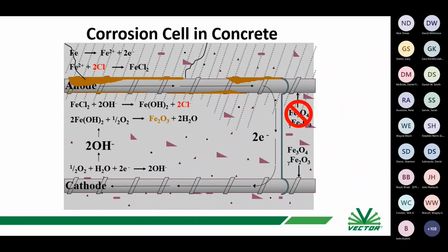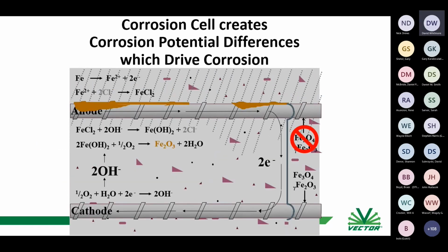So people are generally only concerned about the physical impact of this reaction that's happening inside the concrete. And that's okay, because that's ultimately what's causing the damage. But it's important to understand what's causing that physical change in materials. Okay, so I said very simply that the chlorides getting in there cause this to happen. That's true. Or if it becomes carbonated, that will cause this to happen. But there's really one other part of the equation that you can see very clearly when you go and do certain types of measurements on site.